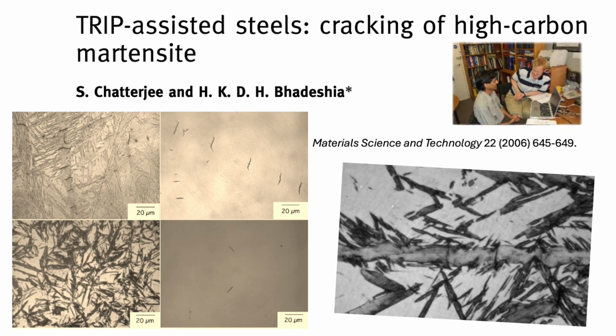Thermal stress. This comes directly from that temperature difference we talked about, the gradient between the hot core and the rapidly cooling surface. Okay. Let's take an example from the sources. A 100 millimeter diameter steel bar quenched from 850 C into water. Pretty standard scenario. You get a big temperature difference. Huge. Early on, the difference between the surface and the center can hit maybe 500 degrees Celsius. Wow, 500 degrees difference inside the same piece of metal. Yeah. And a temperature difference that large, if the steel couldn't relax at all, could theoretically generate stress over 1,000 megapascals. 1,000 MPa. That's enormous pressure inside the steel itself. It really is. It shows you the violence of the process.